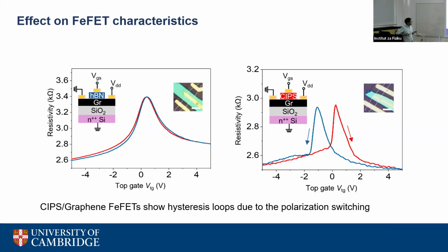And we see when we use hBN, which is a dielectric, you just see a normal Dirac peak because that is just a dielectric. But when you use the ferroelectric, you can see two bistable hysteretic loops. And these two loops are due to the two polarization states in the ferroelectric. This is a ferroelectric FET. And the two loops here occur due to the polarization switching in the material.